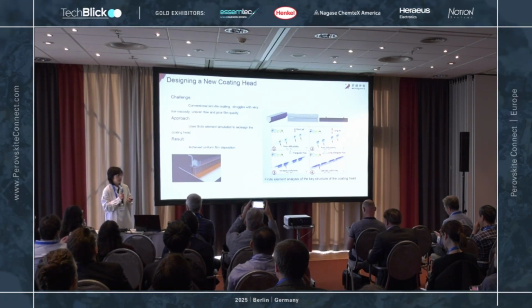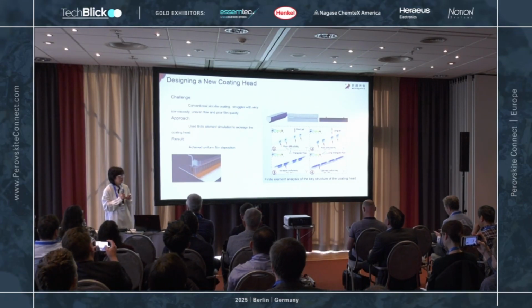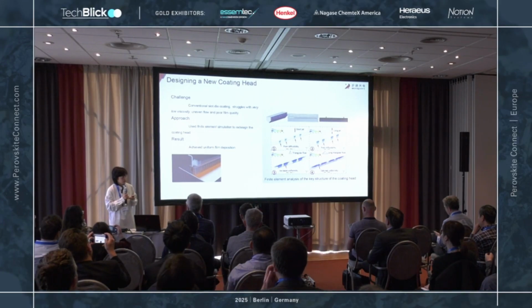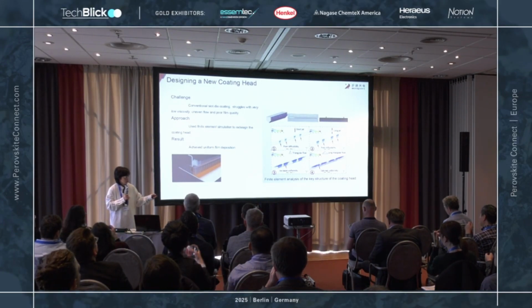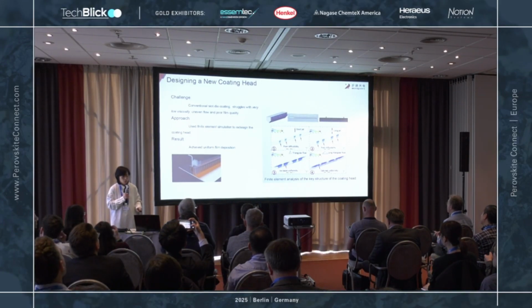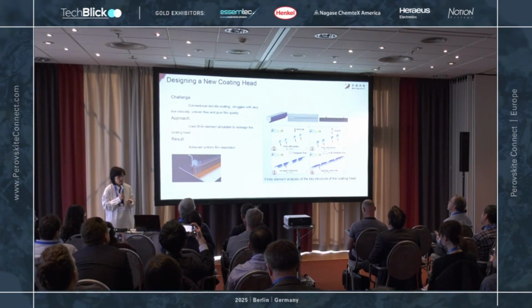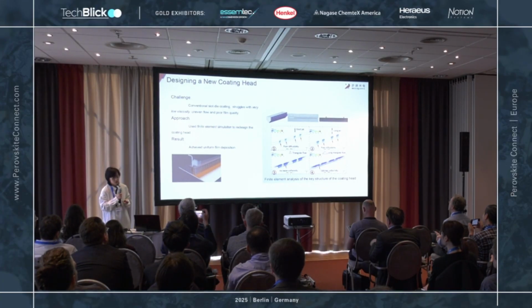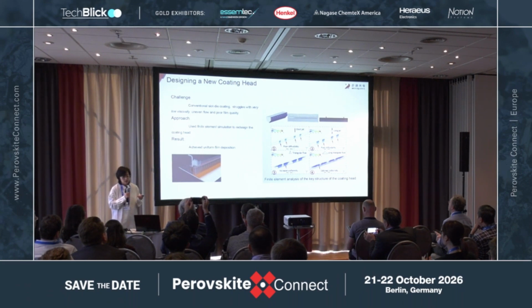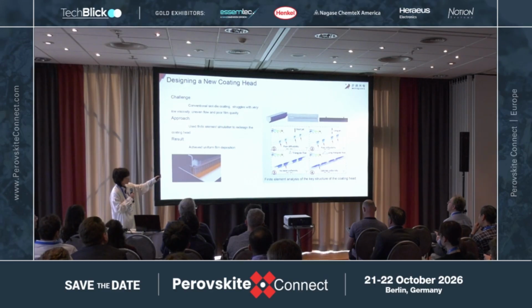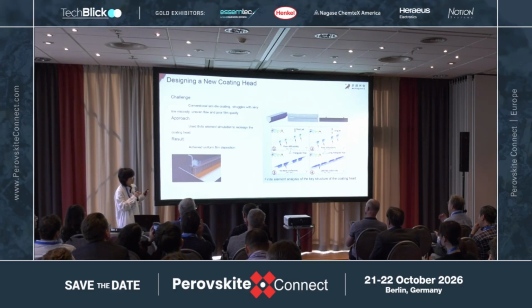To tackle the challenge of forming an even wet film distribution on a large-scale glass substrate, we redesigned the coating head. By utilizing finite element simulation, we redesigned the geometry and function of this coating head, and you can see from the red pictures that gradually we refined it to get a uniform distribution.